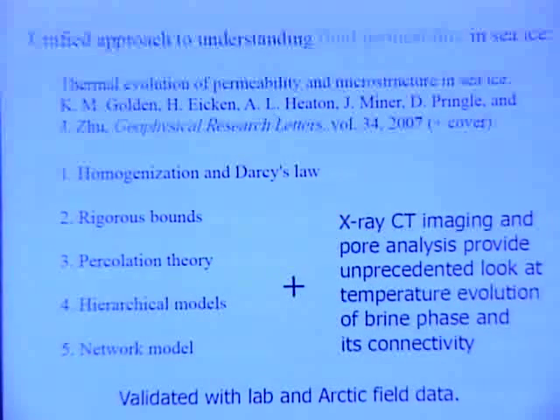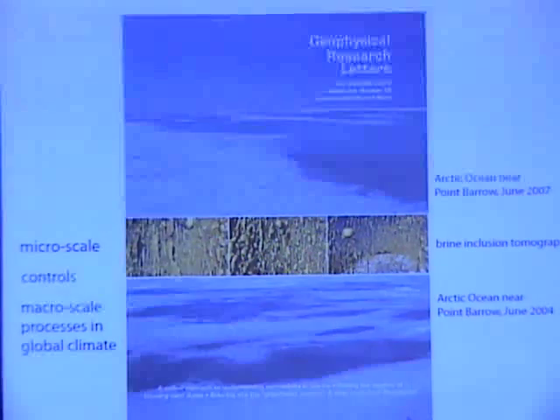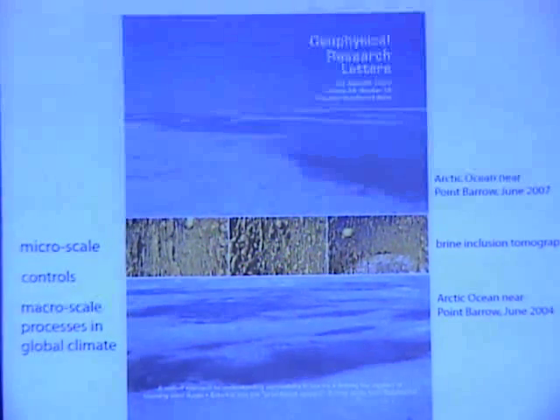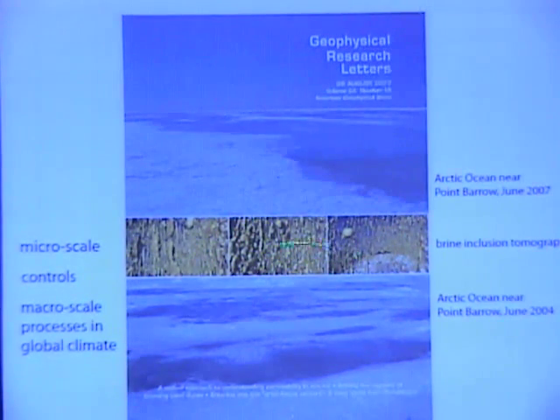And in particular, before our work, people had relied pretty much on sectional photos to analyze the brine inclusions in sea ice. And we developed an X-ray CT imaging way of looking at this, which provided a really unprecedented look at the thermal evolution of the brine phase, and in particular, its connectivity. This is the cover of Geophysical Research Letters, showing, from my perspective, homogenization in action, how the microscale, some of our X-ray tomography, controls these larger scale issues of importance to global climate, such as the evolution of melt ponds.